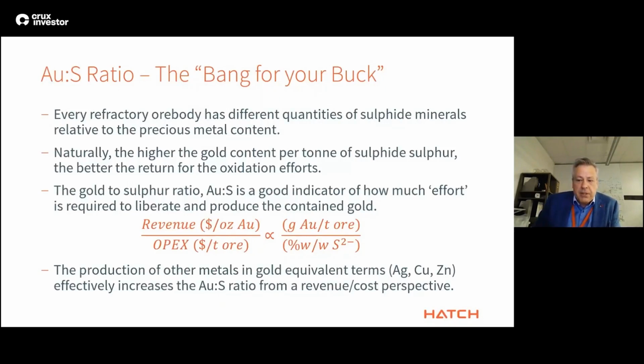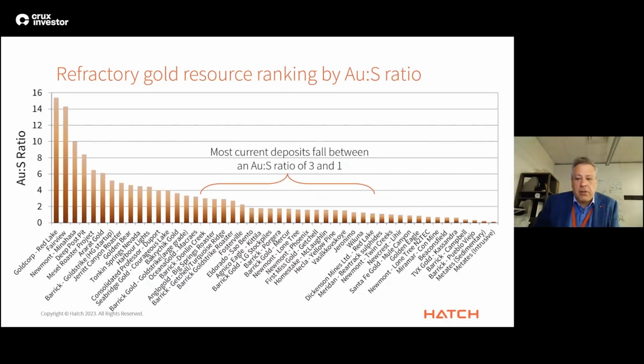The recovery of other metals can also be expressed in gold equivalent terms by converting each metal grade into an equivalent grams per ton of gold using the market prices from any metals exchange. Using the gold to sulfur ratio as an indicator of the relative return on treatment of a refractory ore body, various resources and projects can be ranked in terms of their economic attractiveness to producers or investors. This chart shows the gold to sulfide sulfur ratio for 48 resources ranging from 15.4 to 0.12, with the most current deposits falling between a gold to sulfur ratio of 3 and 1.